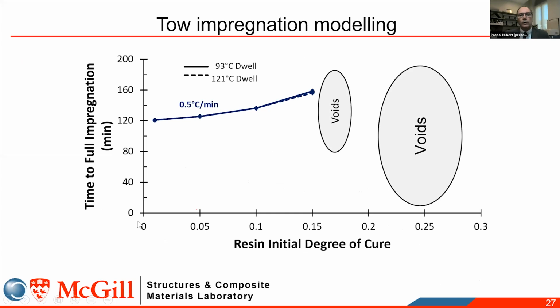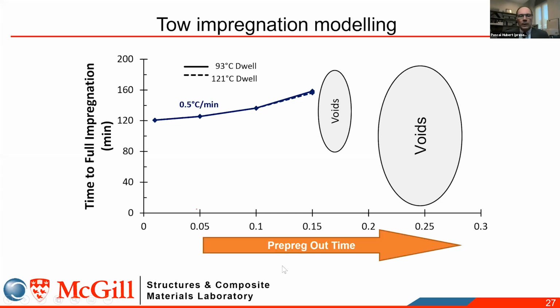Now, with this type of model, we can then run a very simple simulation to look at, let's say, the effect of the resin's initial degree of cure on the impregnation process of that tow. And you see here that if you have initial degrees of cure that are too high, which means that the prepreg would be staying out on the floor for a longer time, necessary to do the layup, you might get some voids.